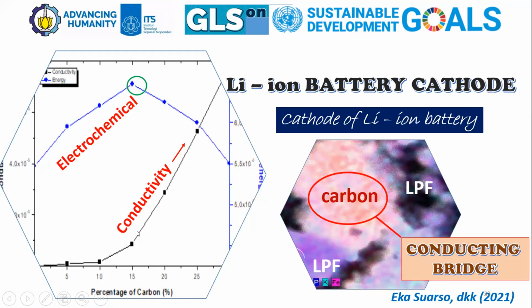You can see here, this is the percentage of carbon from 0, there is no carbon, 5, 10, 15, and so on. It is seen that the conductivity drastically increases as the carbon content increases. But for the electrochemical performance, it increases, and then at the point of 15% carbon, it then decreases. So this is the best percentage of carbon that can be added to the LFP material as a cathode of lithium-ion battery.